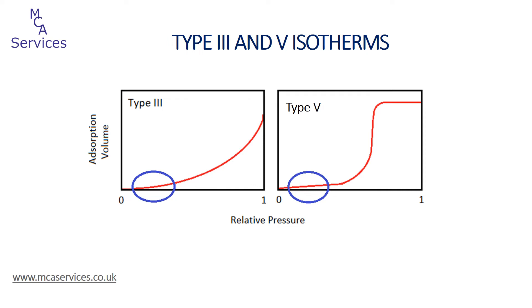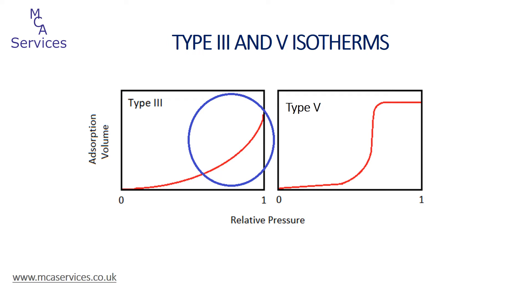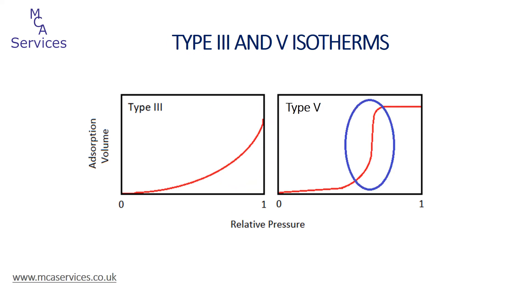At higher relative pressures, both profiles show an increase in adsorption volume. With the type 3 isotherm this could be due either to multi-layer adsorbate-on-adsorbate adsorption — applying to a non-porous sample — or to incomplete pore filling of a macroporous sample. The actual adsorption volume gives a fairly good indication of which is occurring, as multi-layer adsorption will tend to produce a very low adsorption volume. With the type 5 isotherm, the adsorption volume commencing at lower relative pressures than the type 3 is usually associated with the filling of mesopores or small macropores actually present within the sample — so it's generally genuine porosity rather than multi-layer adsorption.